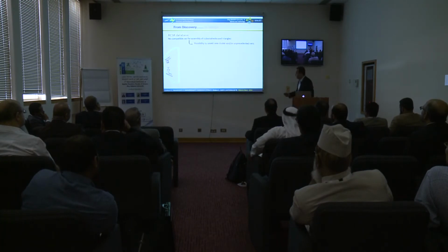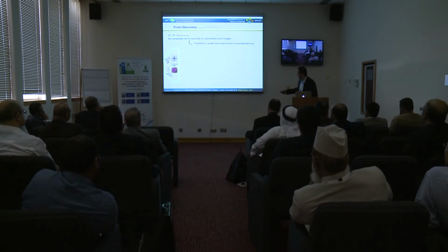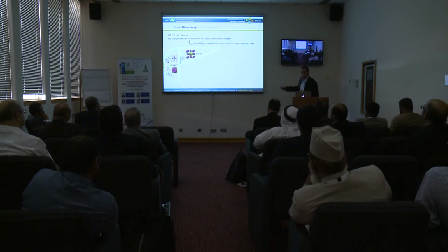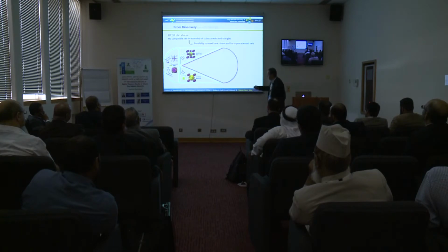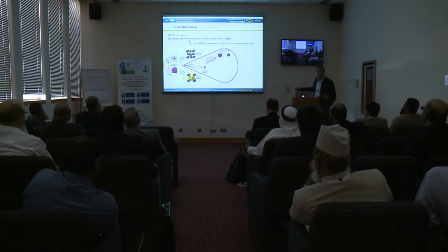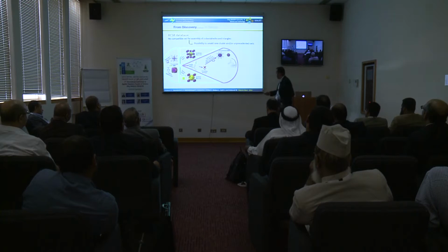So I'll go first here, building block, fluorobenzoic acid. You make this cluster. I showed you FCU. If you take it with the square, we make FTW. This is very easy to make. So you can make this structure here. But if you take this with the triangle, they're not compatible. We have now a cluster that evolves to make a cluster that can accommodate this triangle. So you can see here that topology and chemistry work alongside.